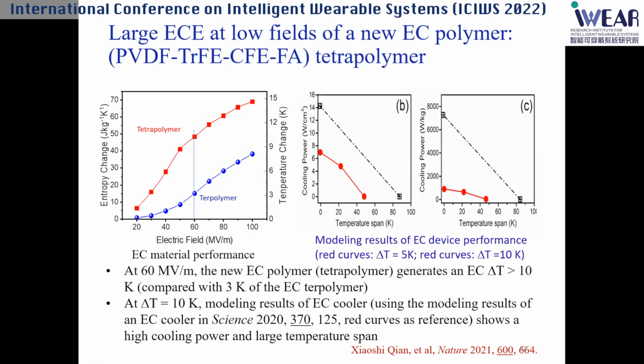Also using modeling results published in Science in 2020, this is for EC temperature change of about 5 Kelvin. But if we get 10 Kelvin, the performance can be very impressive. For example, if we want 20 degree temperature difference between hot and cold air, we can generate cooling.